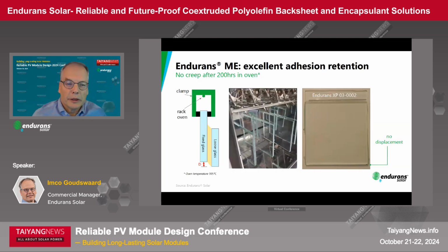A question we often get is, your core layer is not cross-linked, doesn't it start to creep? So of course we did a lot of creep tests there, with two vertical glass plates with the encapsulant in between. We put that in the oven for 200 hours and measured the displacement at 105 degrees C. And we did not measure any displacement. So the temperature resistance is high enough for the PV module application. Next slide.